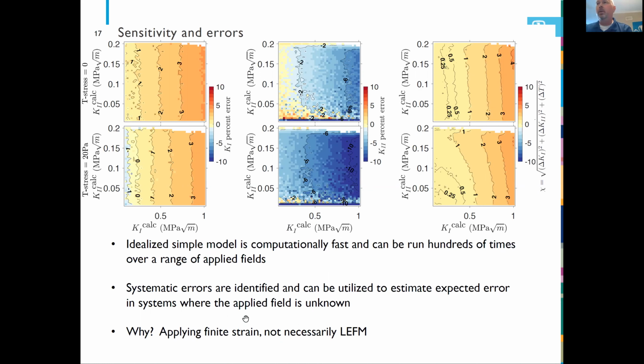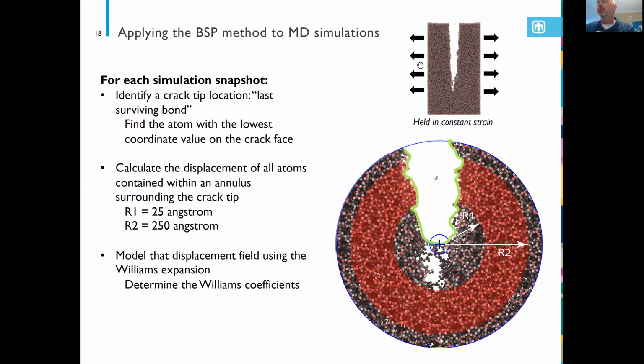Let's apply this whole methodology to our fracture samples. Now keep in mind that what I have in terms of our fracture samples, again, we're holding this type of silica configuration and uniaxial tension, and we're watching a crack propagate, right? So with molecular dynamics, the idea is that you take a snapshot in time, so you're sampling in time on a regular interval.